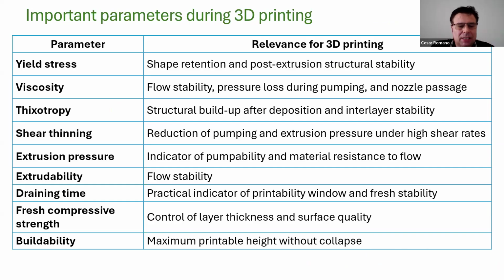Instead of focusing on a single parameter, this strategy that we are proposing aims to characterize the material response across the different rheological stages of the printing process. For example, we need to understand the yield stress of the material, the viscosity, thixotropy, shear thinning, the extrusion pressure, the flow stability during the extrusion, the draining time. We need to understand the compressive strength during the fresh state, and we also need to evaluate the buildability.